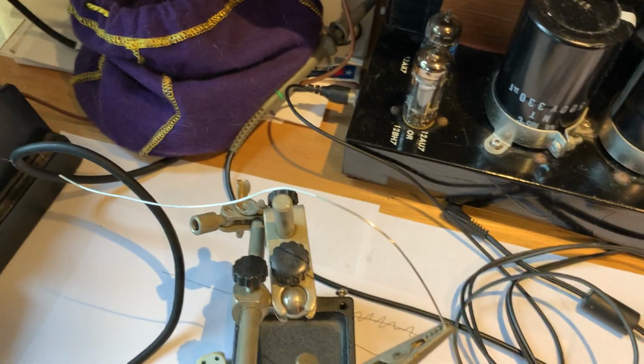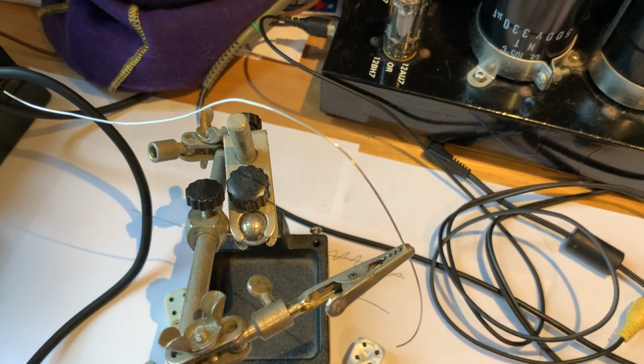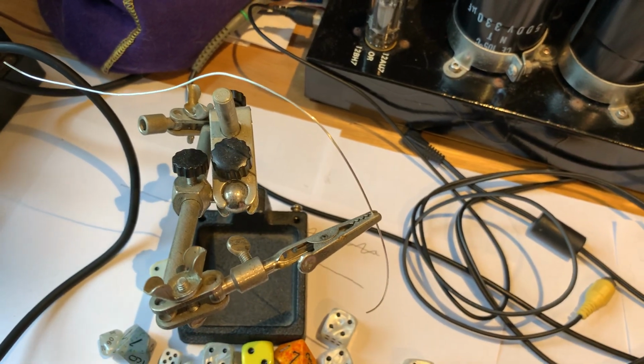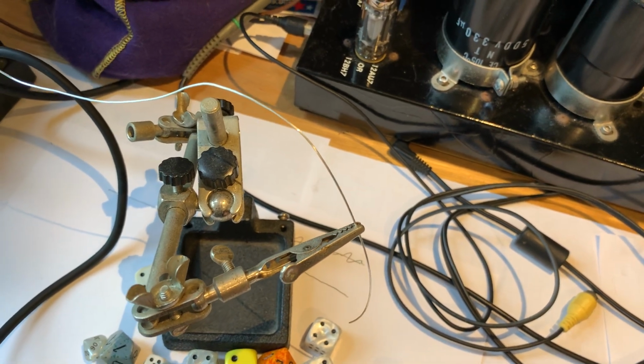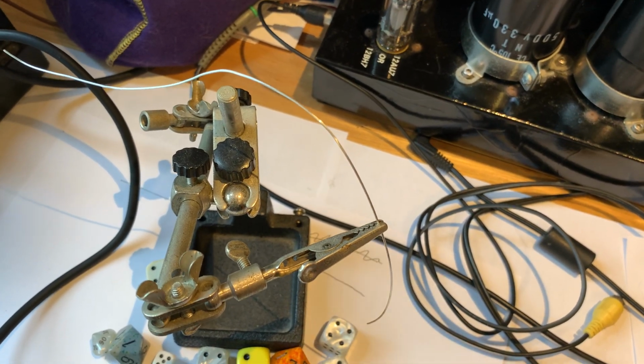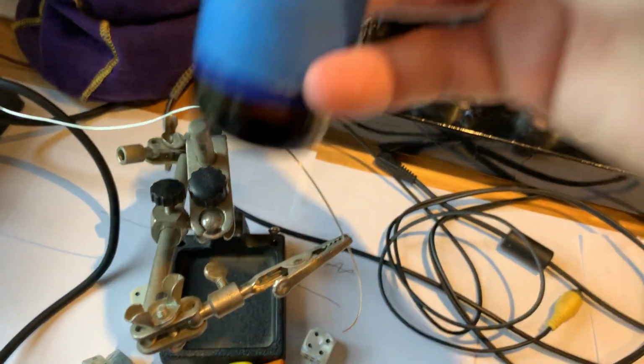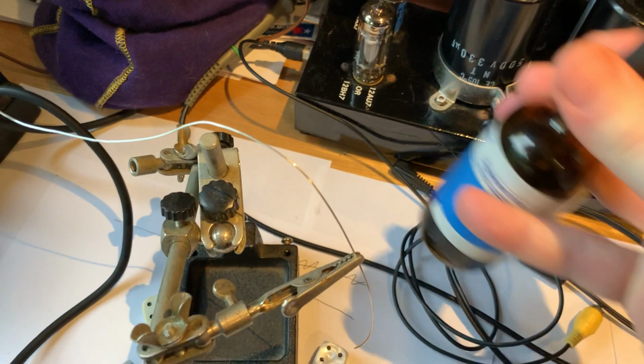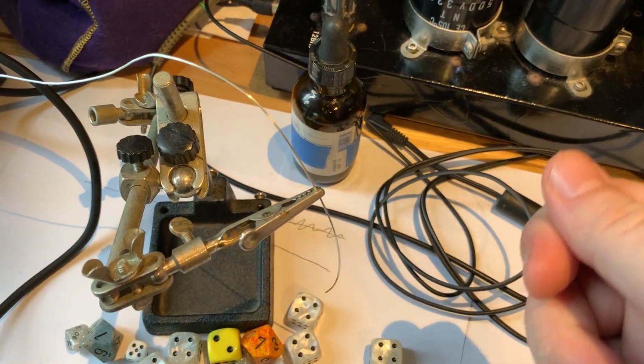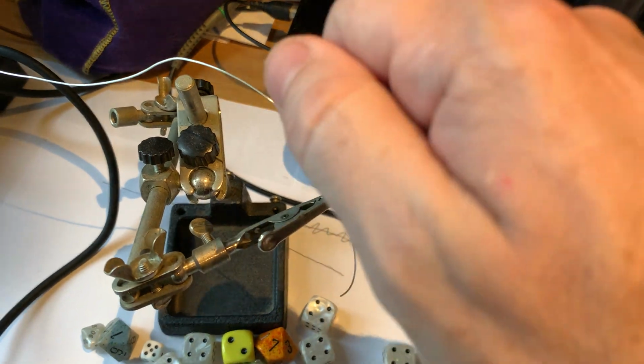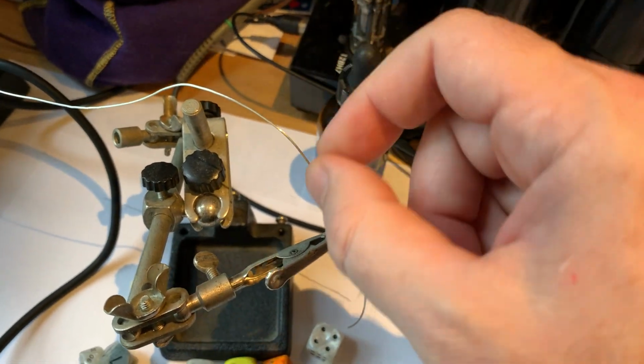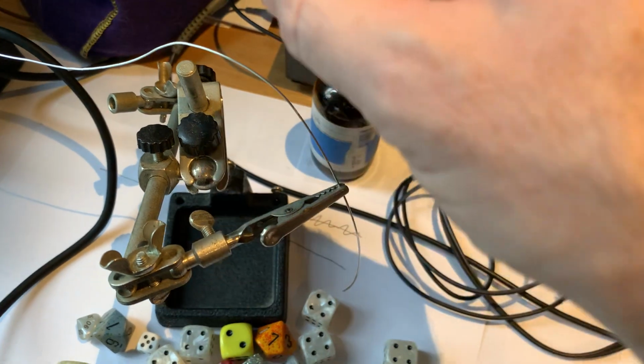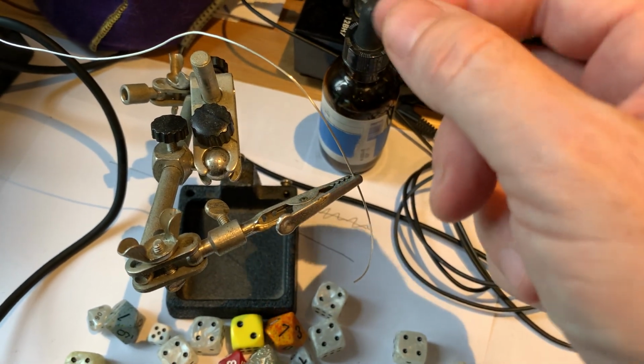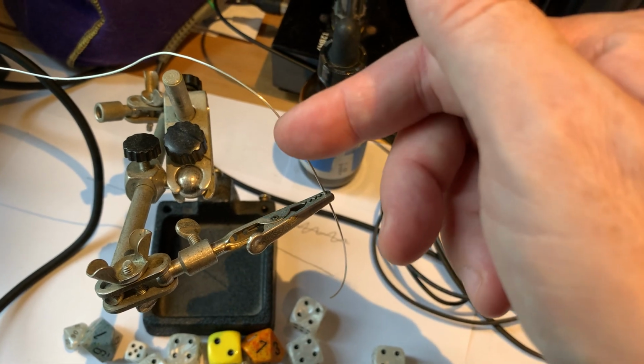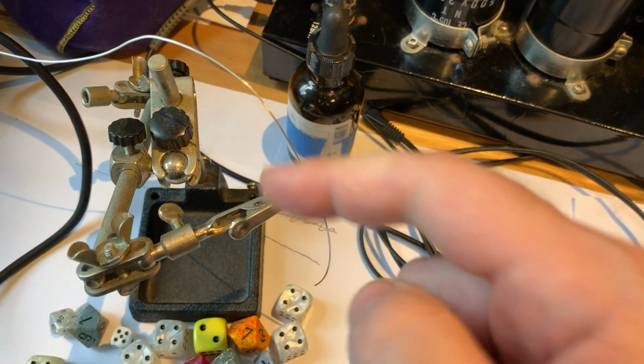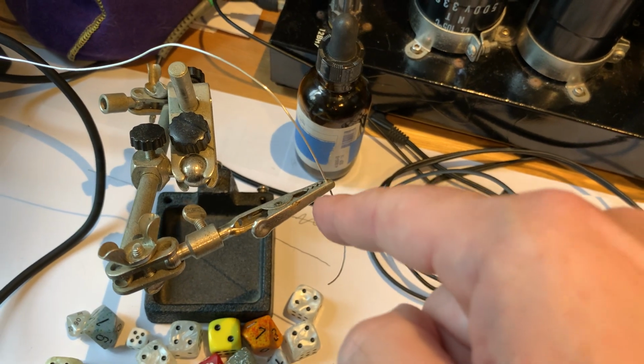If it's not just two wires, but you have a capacitor or a transistor, or some sensitive piece of equipment, then have a little bit of alcohol ready, like 91% isopropanol. That's what I keep in this little jar. Have a Q-tip ready, dunk the Q-tip in your isopropanol, and then put it on your solder joint to cool it down. The heat will be transferred to your Q-tip and the alcohol will evaporate instead of your sensitive transistor dying.